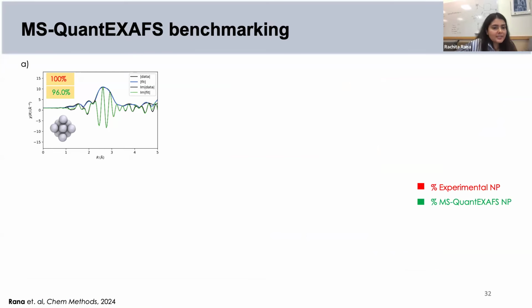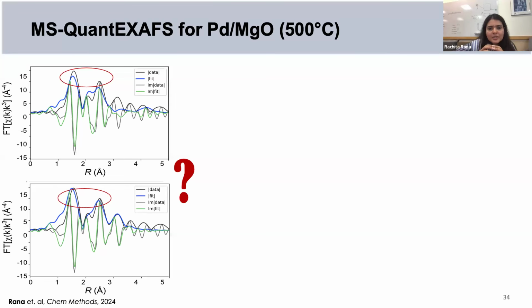This was in situ at the beamline, and so the 700 site was homogeneous, but the 500 site was not. We really did not get a decent fit for the 500 site, the site that was calcined at 500, using any of the structures in our database. And we had accounted for almost all the structures that we could physically think of. And then the idea was, can we use MS-QuantEXAFS to pick a few of the best or decent fit structures that we got from QuantEXAFS, and then take the stable structures from the DFT optimized database to see if MS-QuantEXAFS could answer the question and help us solve this puzzle.